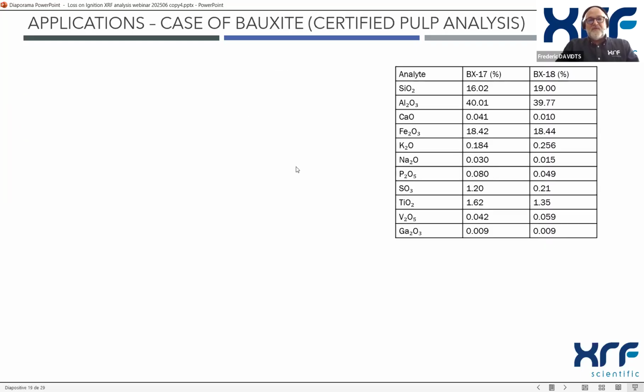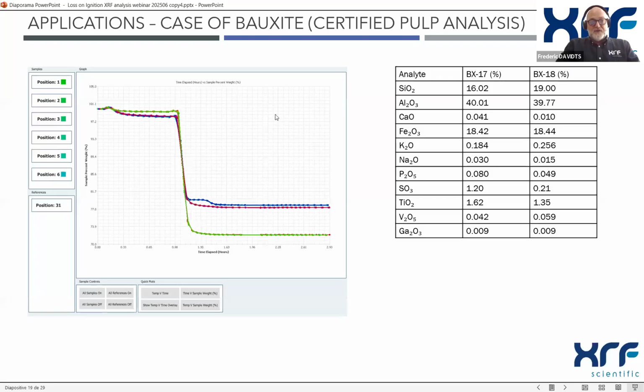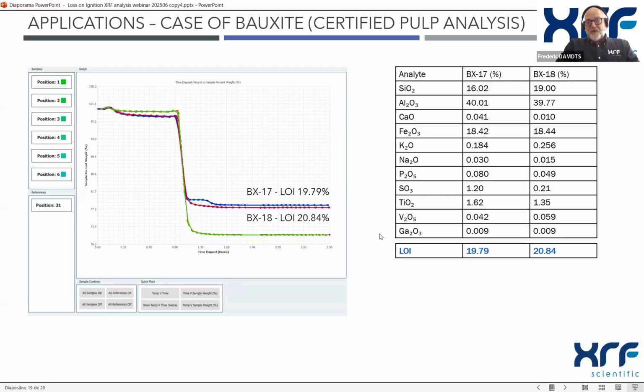So here we have an application with certified bauxite, the BX 17 and BX 18. Here we have the XRF analysis for the 2 standards. When we do the loss on ignition analysis, like I told you, at 2 heating steps, first the moisture and then the LOI at 1000, we reach the LOI value for the 2 standards. And if we add it to the value, we nearly reach 100% of the bauxite. So you can really see that it's complementary to the XRF analysis.